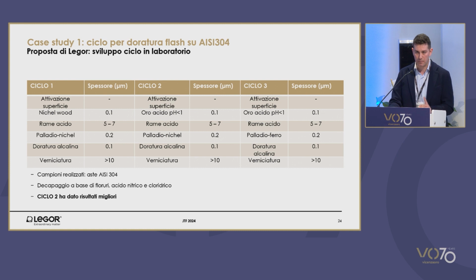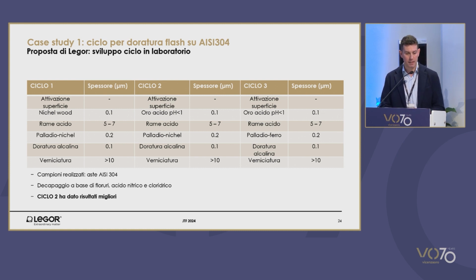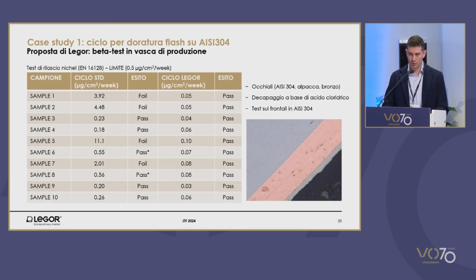In cycle 2, we use palladium. In cycle 3, we only use a nickel-free layer, and it was palladium iron that was used. Performing the release test, we saw that cycles 2 and 3 were giving the best results. This means that nickel did contribute to the release of nickel. Cycle number 2 is the one that was tested because it was more similar to the cycle that we resorted to earlier with palladium nickel.